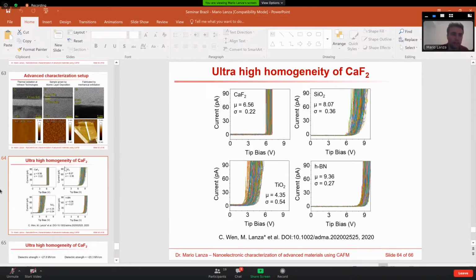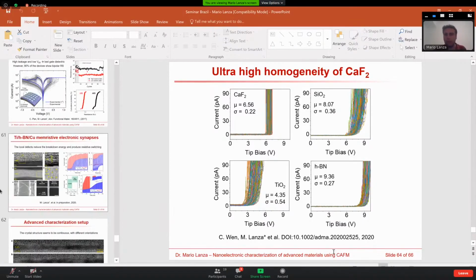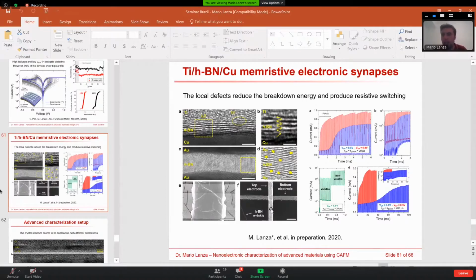However, right now we are doing one study that consists of trying to calculate the band gap, the position of the energy bands, and the formation energy for vacancies in locations of the boron nitride that are perfect layer or that contain some defects. This can be done by DFT or by ab initio methods. So I think there is space for people working on simulation to complement conductive AFM studies. It is a very good match.